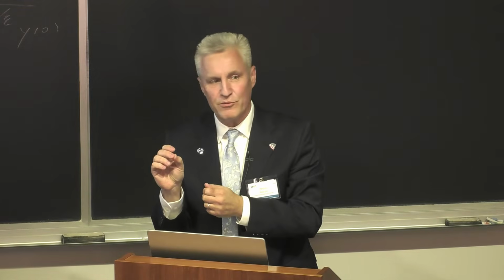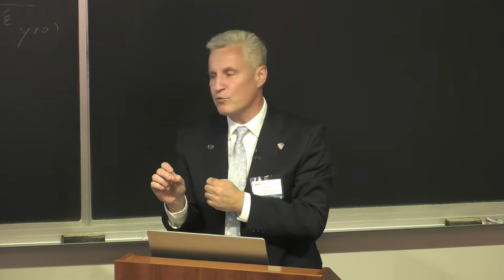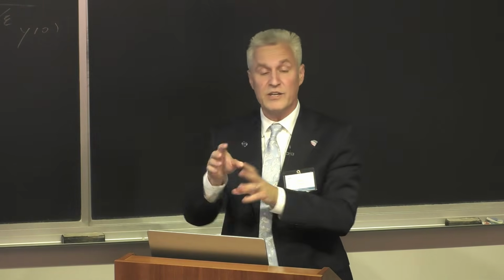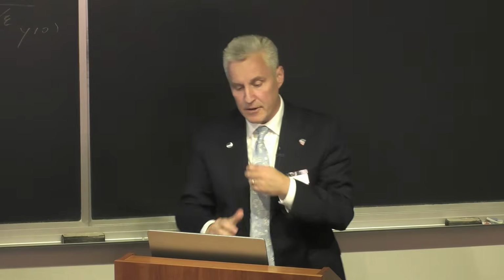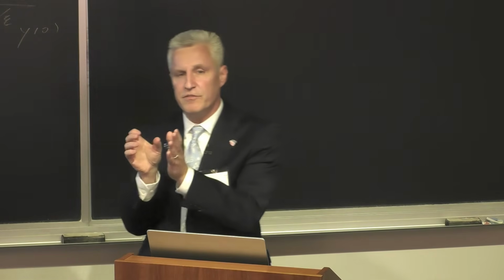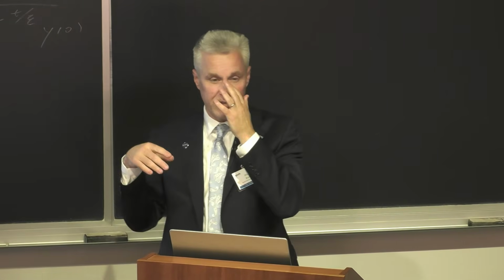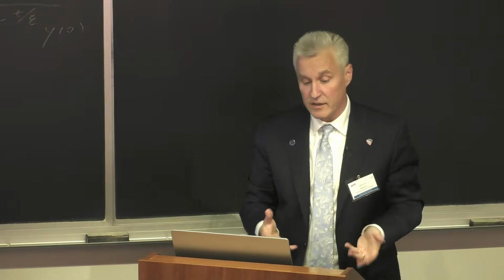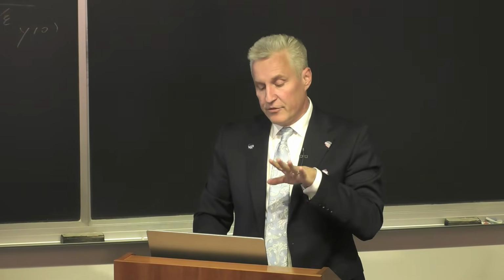And the more you dig, you start to realize people are not actually seeing the Butler-Volmer equation in most cases where they say they do. It's because they're doing that kind of fitting. So I'll come back to that again, but the important thing is that a film resistance, whatever it is, should be temperature dependent. So that was our argument here, that in Marcus theory, lambda is actually not temperature dependent. Okay, so that was the starting point.